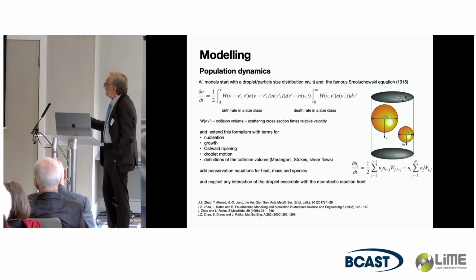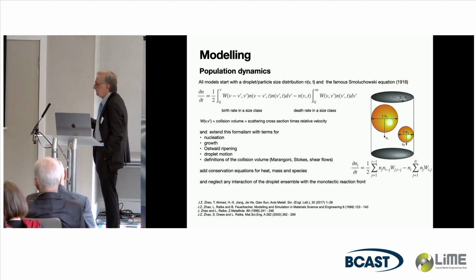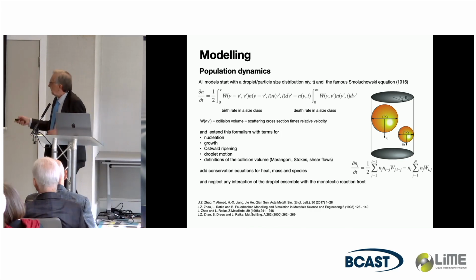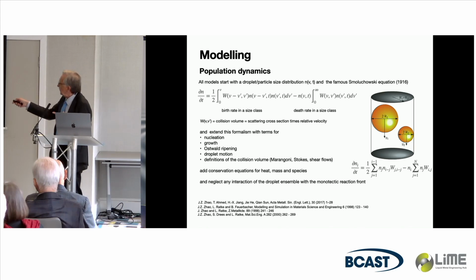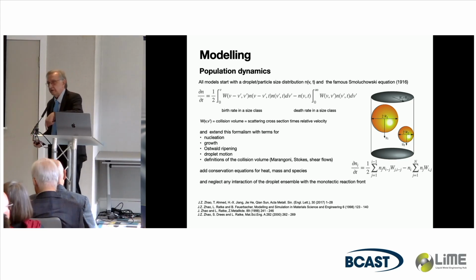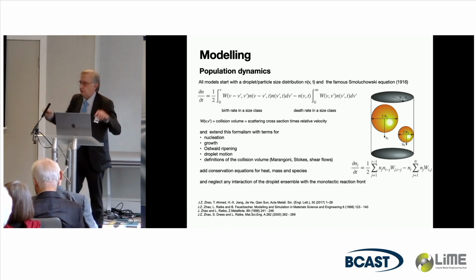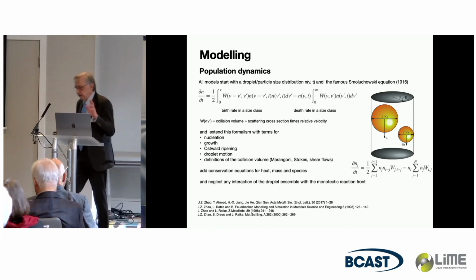Okay. So then, of course, this is not how you describe the complex phenomenon in immiscible alloys. You add a nucleation term on the right side, you add a growth term on the left side, you can add, but need not, Ostwald ripening and droplet motion also on the left side, which makes it then space dependent. So it's another variable. And of course, you have to have some definition of collision volume, which is difficult.